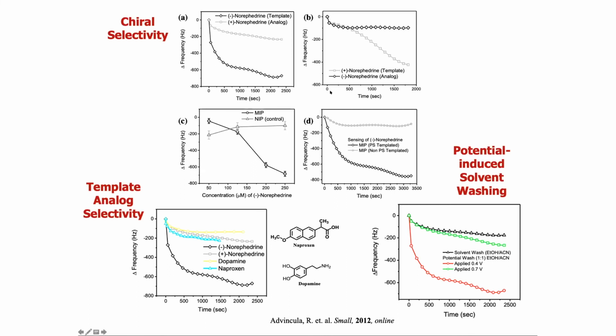The decrease in frequency means that you have binding, or high binding kinetics, of the analyte on the original template, which was exhibited by the MIP, but not with the NIP or non-imprinted polymer film. Moreover, when we did the selective or competitive binding, naproxen or dopamine, which were not the original template, did not bind on the surface, but only the original template. And lastly, solvent washing with application of a potential or voltage results in a more efficient sensor than one without it.